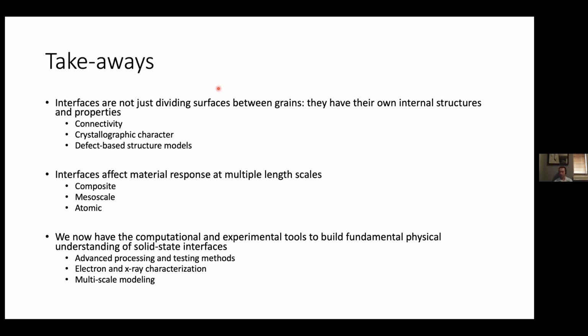The plasticity that occurs near the tip of a propagating crack will dissipate energy from the crack. It'll impede the crack as it travels. And so the easier it is for something to plastically deform, typically, the more difficult it is to propagate a crack through it. One of the big challenges in materials science, and this has been a long-standing challenge for many decades, is to get away from that trade-off to create materials that are both tough and hard. That's not easy. There are strategies that people have come up with, but as a rule, as a zeroth order response, there is this trade-off between those two properties. Very good, thank you. Thanks.